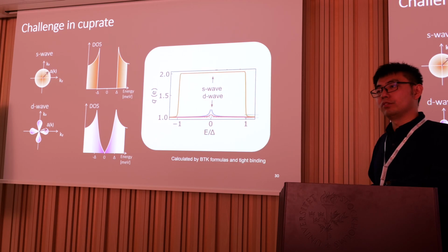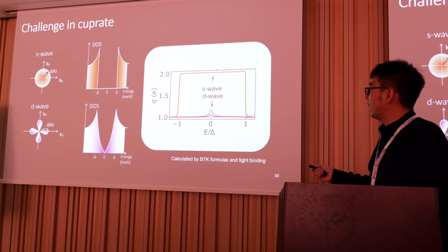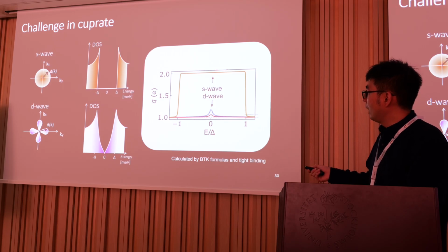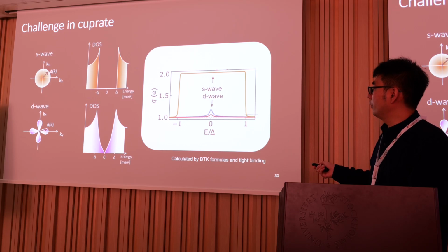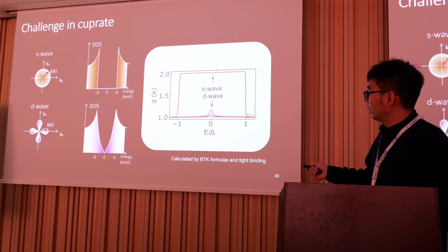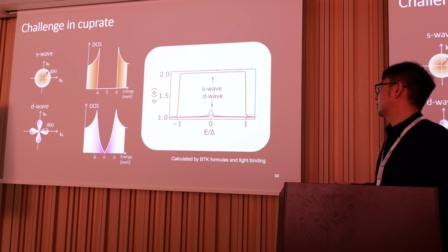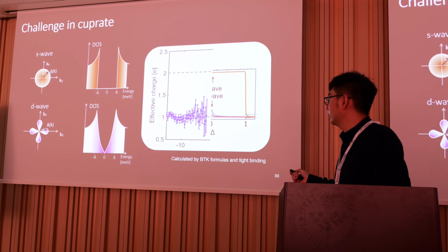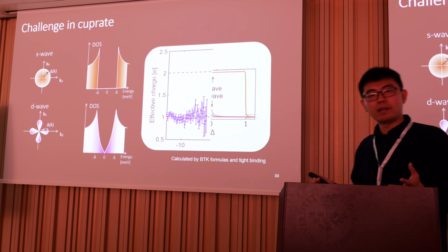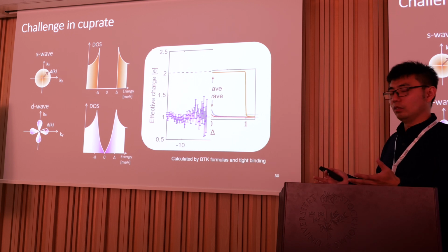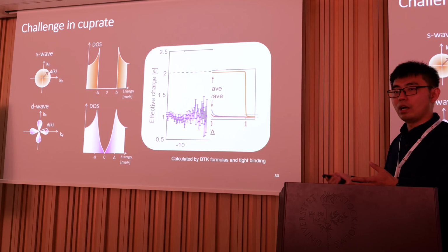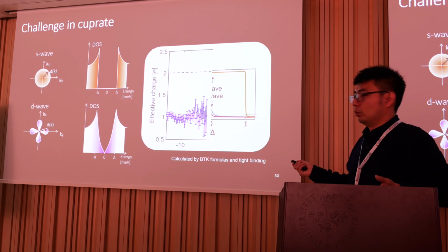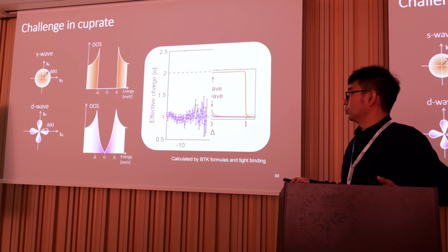We can do some simulation for the D-wave and S-wave. You can find that for the S-wave, it's clear you change from 1e to 2e, this is effective charge versus energy. And for the D-wave, this is calculated for the single gap scenario, and you can find that it's much smaller than the S-wave. And if you compare the experiment results with the theory simulation, you can find it makes sense. You should not measure anything now, but unfortunately, this is already one of the best resolutions at that time. But you know, this means it looks like no hope, but it doesn't mean we should give up.